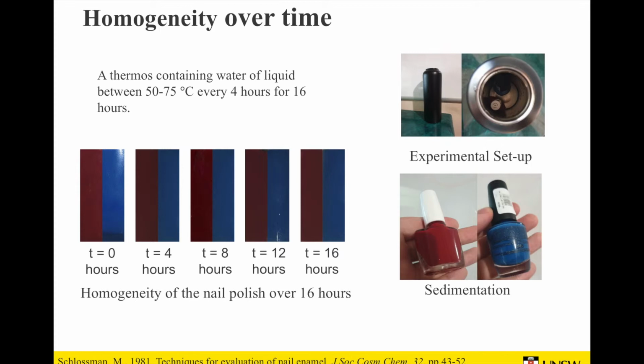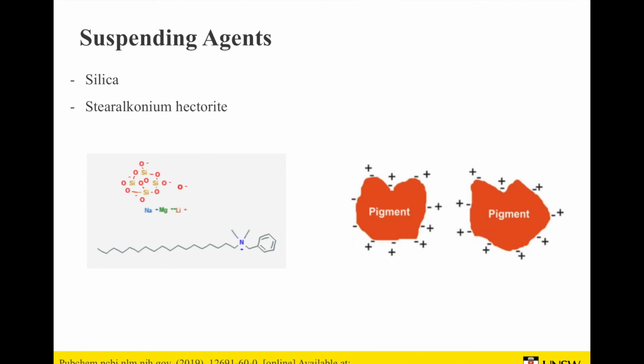To perform an experiment that could simulate a long timescale, the bottles of nail polish were placed in a thermos while submerged in water with temperatures varying from 50 to 75 degrees Celsius. The temperature was measured every 1 hour to ensure it was within the range, as well as the photo taken every 4 hours. The following are pictures of a nail polish over time. As we can see, there isn't much change to the homogeneity of a solution. However, after 16 hours, the blue nail polish demonstrates a small degree of sedimentation. Our nail polish utilizes silica particles which create a thixotropic system, which builds enough viscosity to discourage pigment settling. Stearalkonium hectorite is also used as a suspending agent which attaches onto the surface of pigment molecules, making them hydrophobic, raising the degree of dispersion.